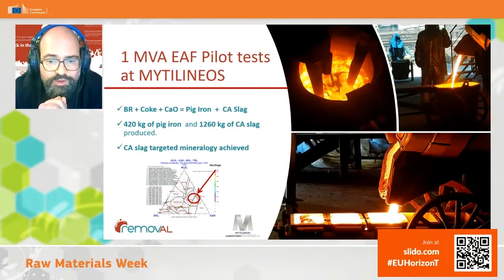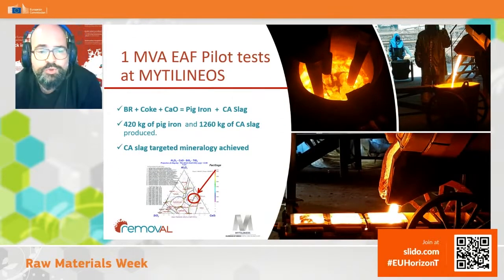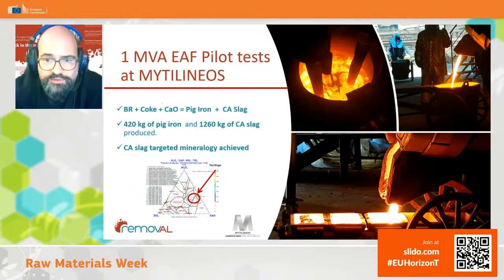Next slide. Also at Mytilineos, we tried a different recipe, again with EAF smelting, this time in a slightly bigger furnace, where our goal was to extract pig iron and at the same time fix the slag in a very specific chemical system, to form calcium aluminate slag. So we did some tests and achieved the mineralogy we wanted. Next slide. And I will come back to the slag in a few slides from now. So next slide.